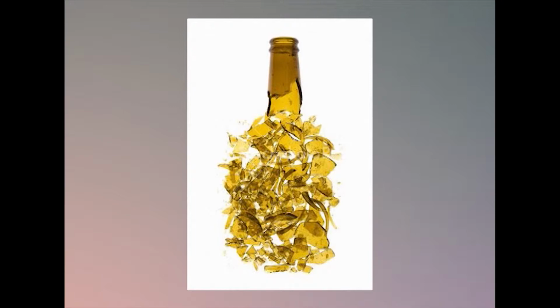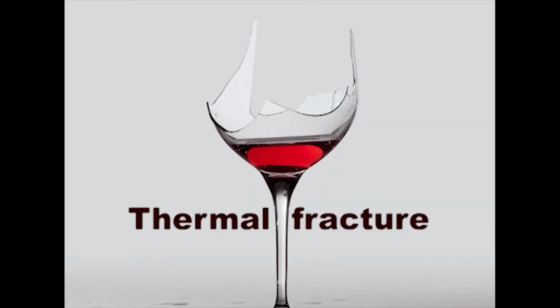After the initial fracture, it often forks at both ends, producing a series of fractures that are symmetrical about the initial longitudinal fracture, that is, in the form of a fan-shaped pattern. As the fan-shaped pattern diverges, it travels through the circumference and separates the neck and base from the rest of the portion. Then comes the thermal fracture.